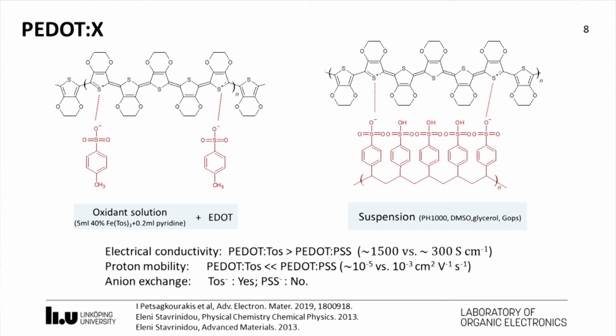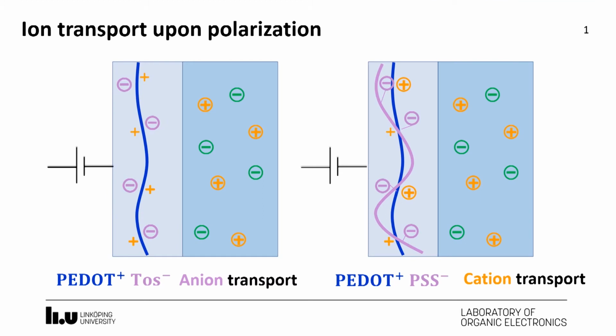with the presence of GOPS, which is a cross-linker, so they are not mobile and exchangeable. This mobility of the counter ion and the exchangeability will result in different ion transport upon polarization. For example, in a PEDOT:TOS electrode, if we apply a negative voltage to de-dope the polymer and then to keep the charge neutralization, this counter ion tosylate will be leaving the polymer. And in the case of PEDOT:PSS, because PSS is not mobile, it will be cations coming into the polymer, resulting in different ion transport in these two polymers.